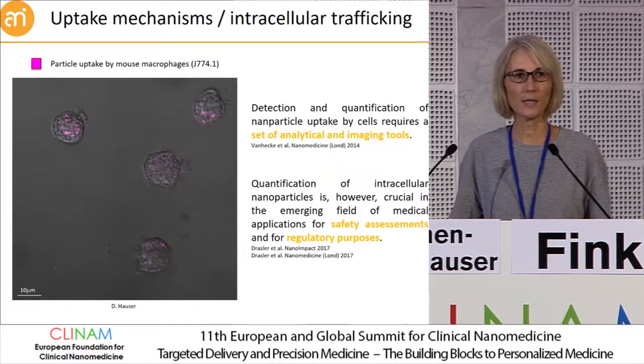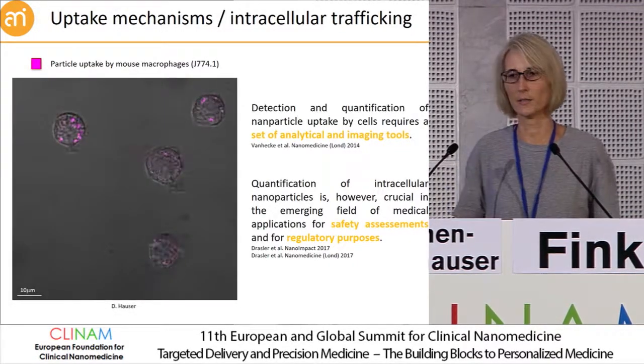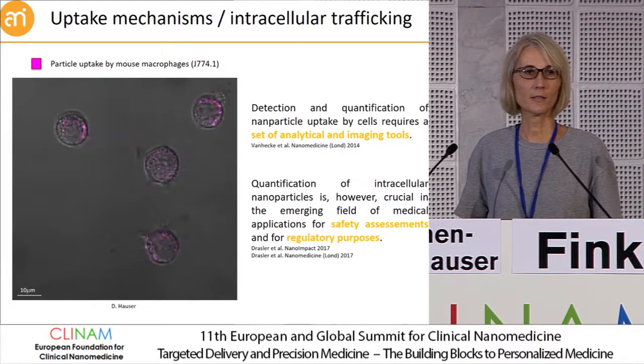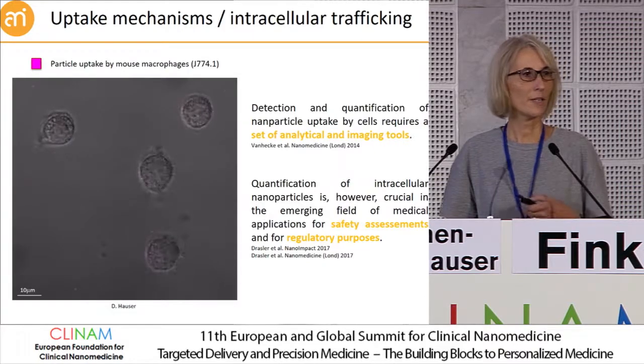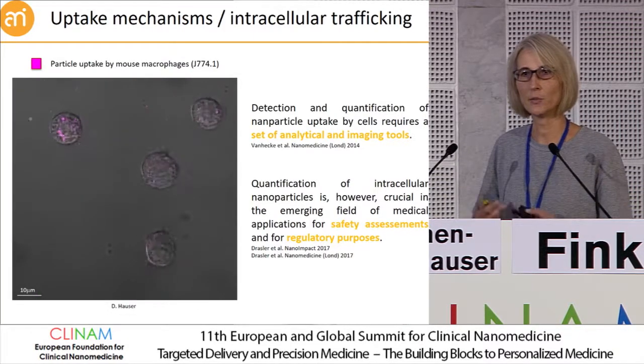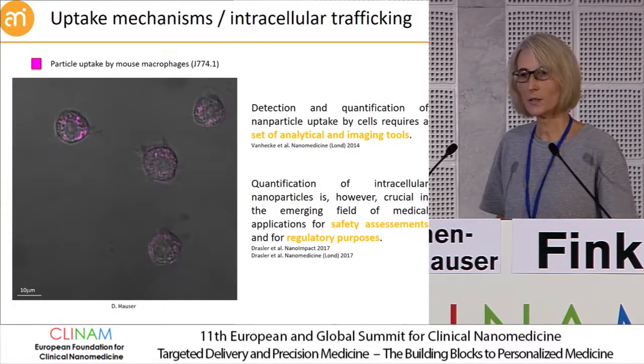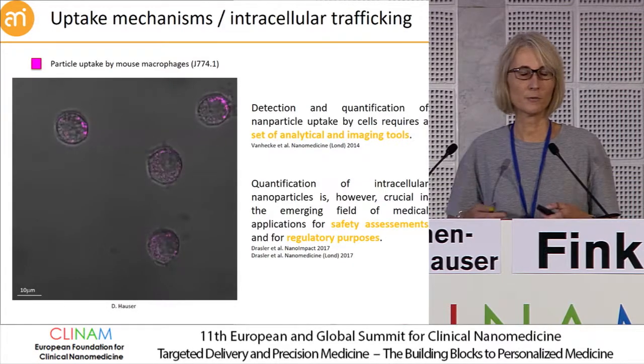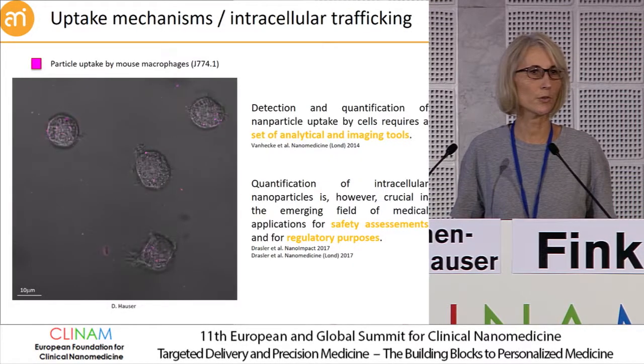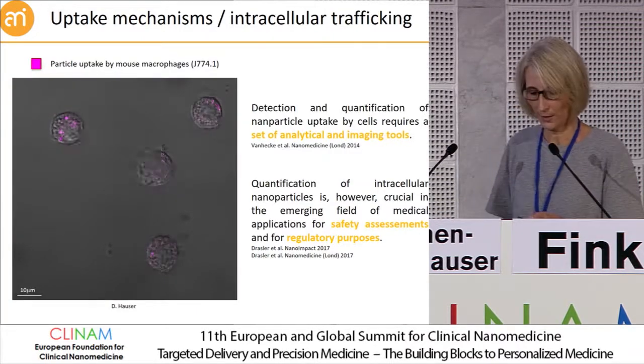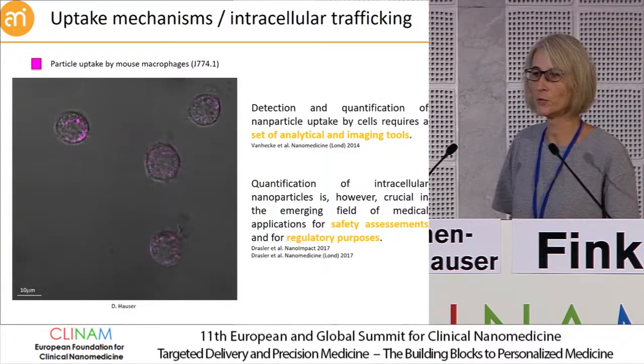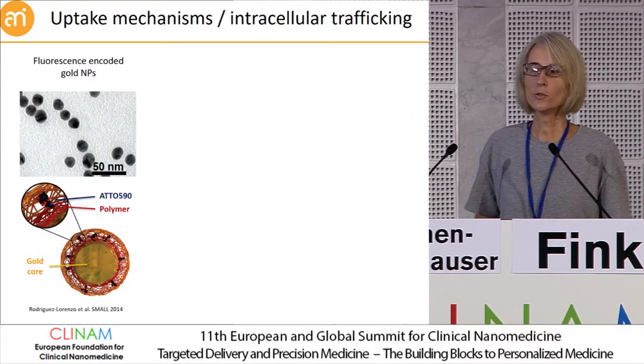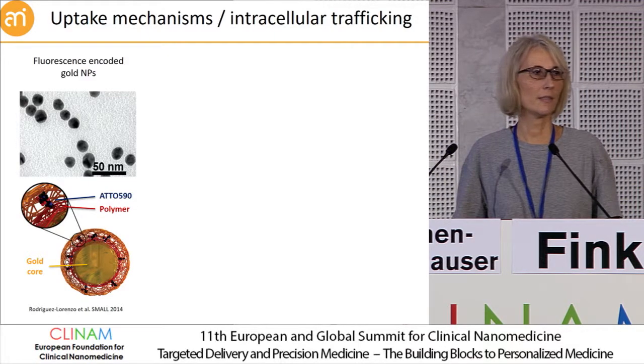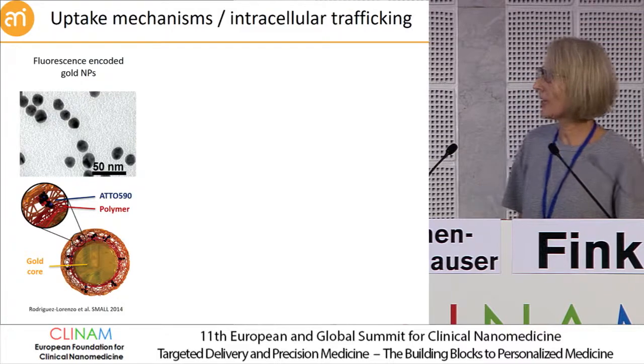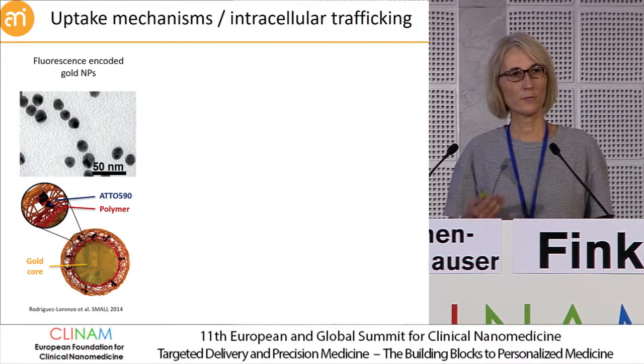We can use chemical analysis, which is of course the same as for particles in a buffer solution. But then for the intracellular quantification, we also need to get rid of the very complex bioenvironment, which can induce artifacts during the measurements. And it is very important that we relate the intracellular nanoparticle concentration to a possible cell response, because this is important for the safety assessment and also for the regulation. So most of us usually need fluorescent particles to assess the distribution of the particles and the kinetics over time. And this is mainly based on detection methods for fluorescence.